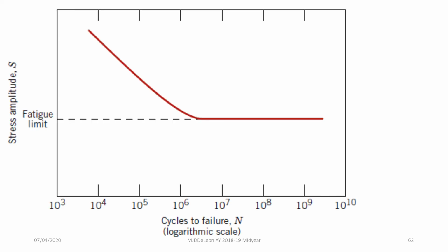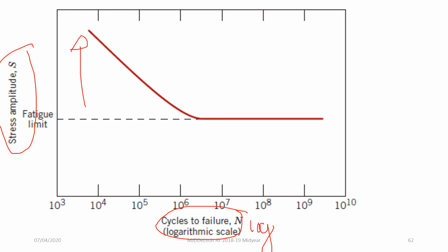So an example of an SN curve is shown in this slide. In this slide, we plotted the amplitude of the stress versus the cycles to failure N. So this is usually in the logarithmic scale or log scale. And makita natin that as your stress increases, the stress amplitude increases, mas konti lang cycles ang kaya ng material mo. And as we decrease your stress, dumadami yung cycles before your material fails.